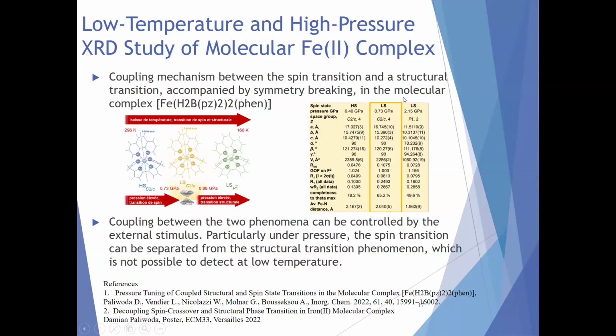So here you have the low spin state before applying the pressure, which is a monoclinic C2/c. And when applying the pressure, we have this breaking of symmetry and we have a triclinic P-1. So this study clearly highlights the preponderant role of the application of pressure to better understand the structural property relationship of a material. In our case, without this high pressure study, we would never have highlighted the fact that the spin transition can be separated from the structural transition phenomena for this molecular iron complex.